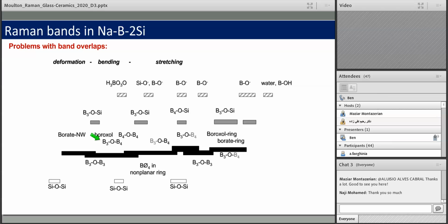Thank you for your question. There are a couple of different aspects to the answer. First is the spatial resolution of Raman, which is quite high, as I mentioned, at the micron level. So if those precipitates have a size greater than a couple of microns, and you can get the Raman beam on them, even at about a micron, so long as it's not much less than half a micron, you can get a good Raman signal if you're willing to take a long enough spectrum. For example, if you have a colorless glass and a colored phase, it's quite easy to identify those minor secondary phases.